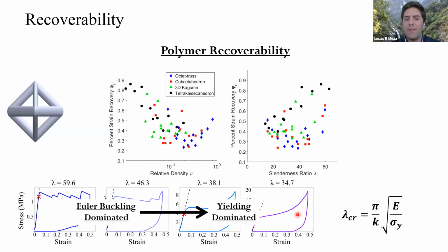But we found that slenderness of the structure didn't actually correlate very strongly to recovery. Density loosely correlated with recovery, but even then there wasn't a strong trend, especially across all the different architectures that we looked at, which was interesting.